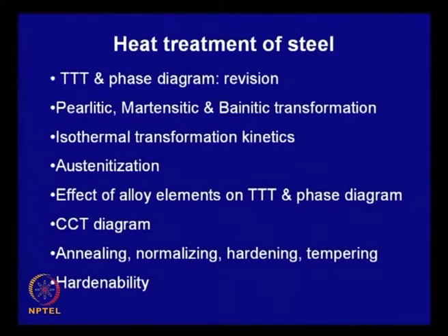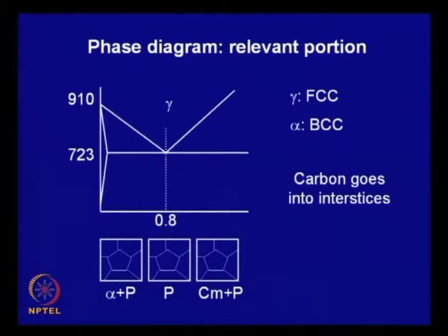When you heat it to the austenite temperature, that cementite or carbide dissolves in the matrix, you have a single phase structure, and when you quench, you retain a high amount of carbon, no doubt. But we will see in this case, unlike precipitation hardening, instead of strength going down, strength goes up substantially, and we will try and see why this happens.